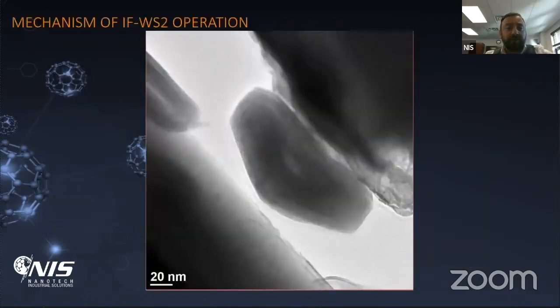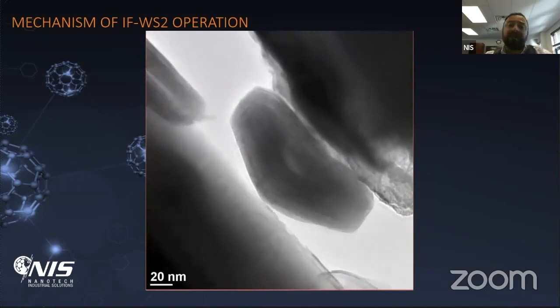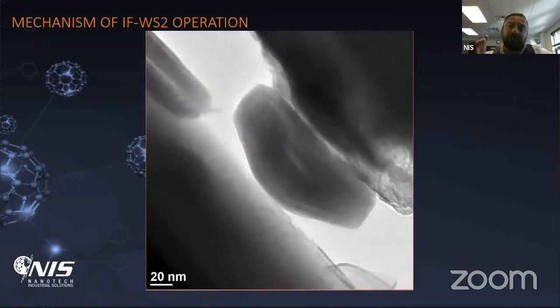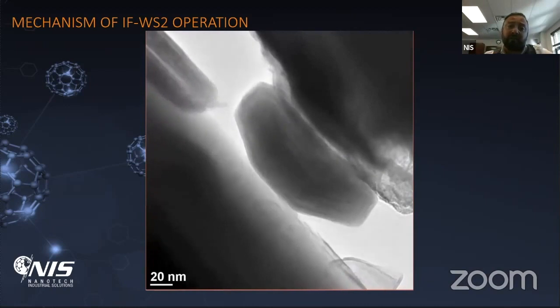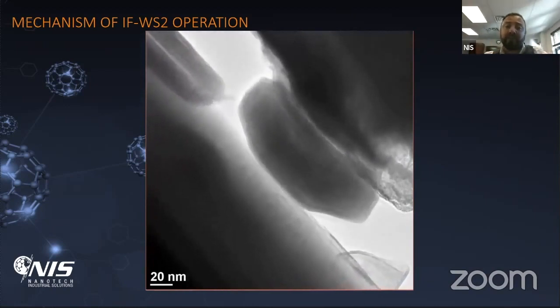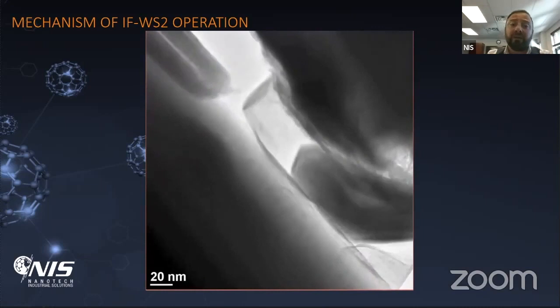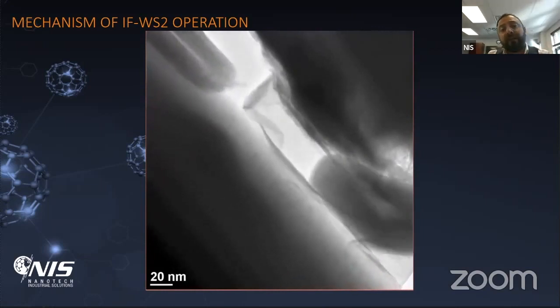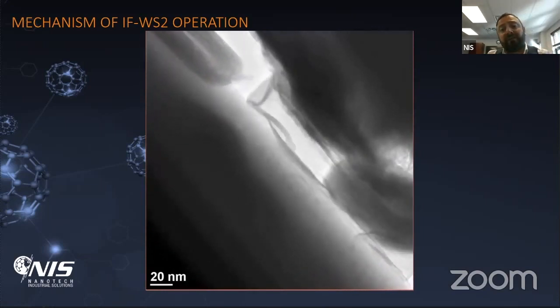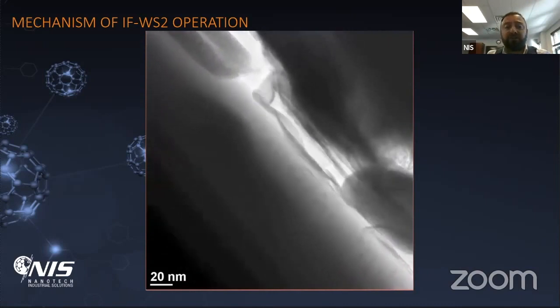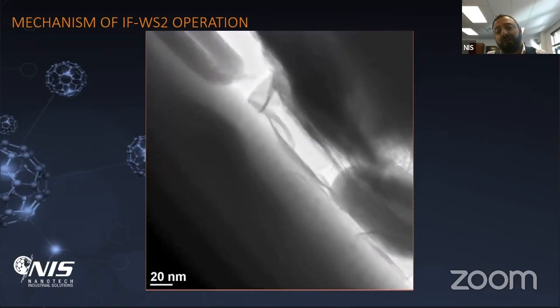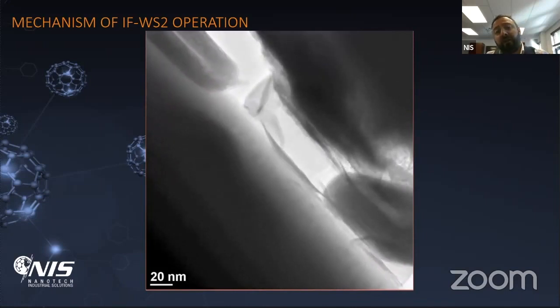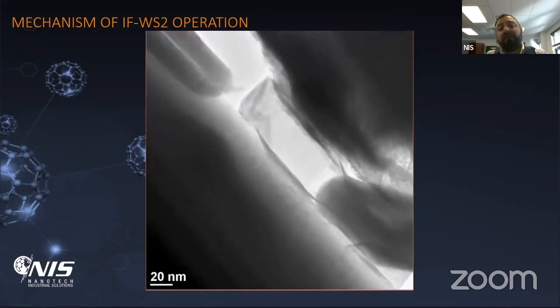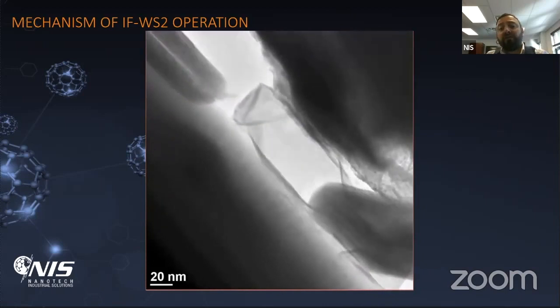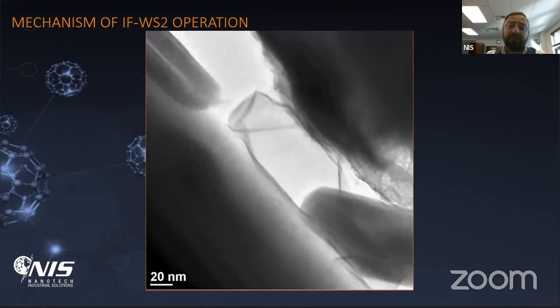So in this video, you're going to see the different mechanisms. Under microscopy, they start compressing the particle, and you can see that it's compressing and has quite good elasticity. At some point, the layers of tungsten disulfide get exfoliated, and that's your friction reduction mechanism, the exfoliation of layer after layer. If you notice, the particle moved to the right, and it bounced back to near its original shape. That's your shock absorbing property.